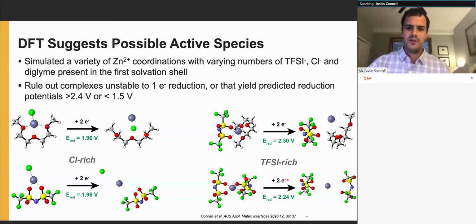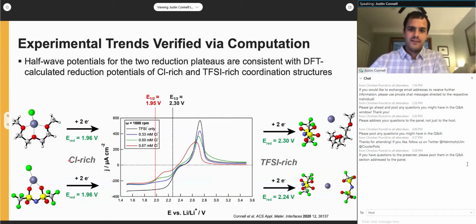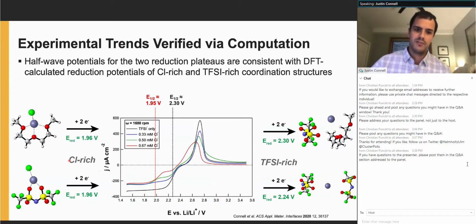And what we see is that the trend predicted by DFT matches very nicely with what we see in the experimental results, where the TFSI-rich coordinations predict reduction onset positive of that with the chloride-rich coordinations. Not only that, these structures actually match very well with the experimentally observed thermodynamic reduction potentials that we see in the voltammetry. And so what this says is that this idea of the cooperative effect between TFSI and chloride leading to the overall more reversible electrochemistry does appear, in fact, to be a reasonable hypothesis.